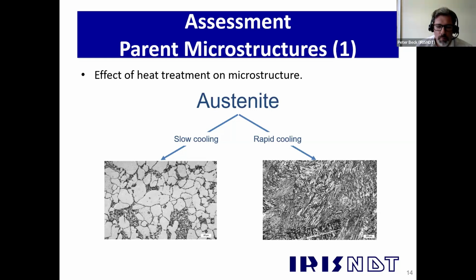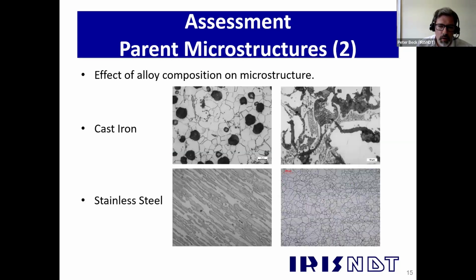The other option is rapid cooling, which stops the carbides from forming into these nice individual grains, and you get this sort of acicular structure, which we'd call martensite. So that's the effect of heat treatment on the microstructure of a metal. And then also the actual composition can have a significant effect as well.